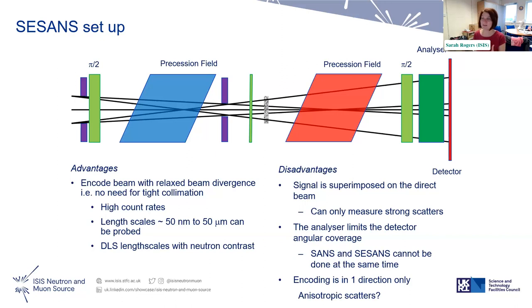There are obviously disadvantages to this, otherwise we'd do it all the time. And those disadvantages are that the signal is superimposed on that direct beam that we're hiding on the SANS detector. So actually your sample has to scatter quite strongly to be able to distinguish it from the direct beam. We have to have an analyzer in place to do these measurements, and that obviously impacts on the angular coverage we can have on the detectors. And at the minute, SANS and SESANS cannot be run at the same time.